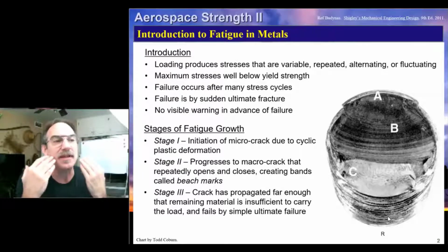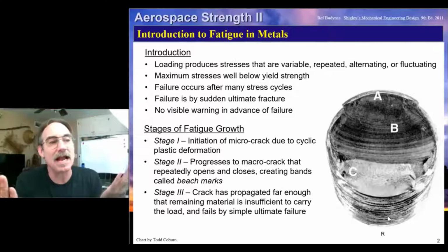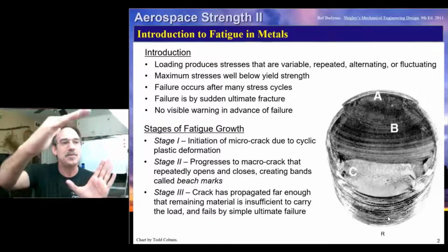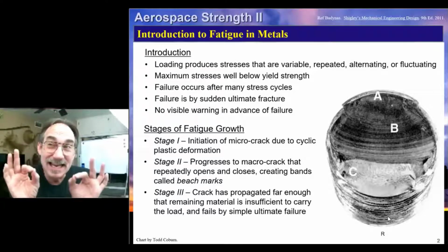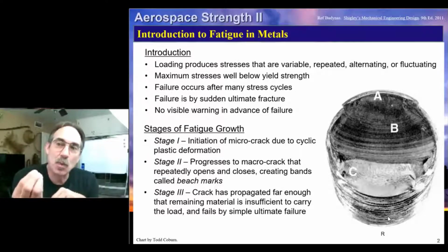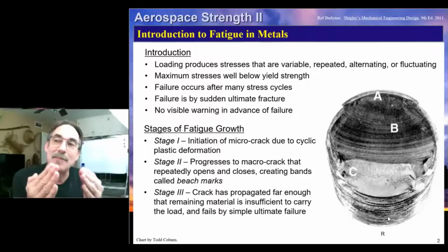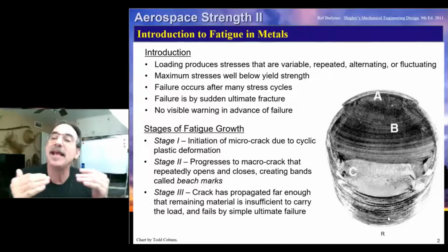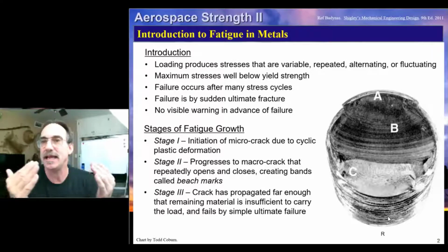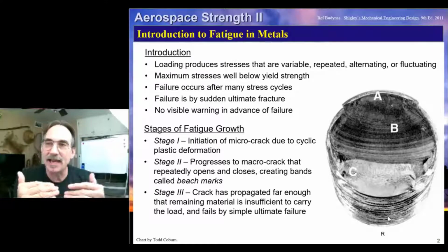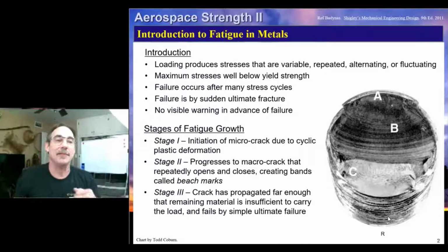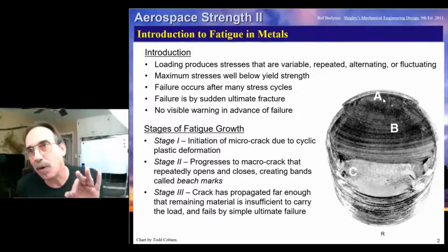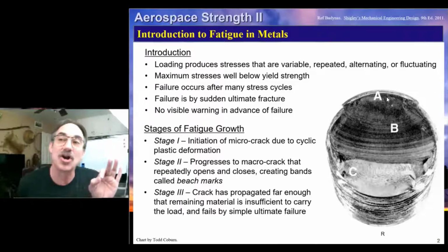If we look at this sample, we say, where did this damage start? With less experience, it's hard to tell. But notice these beach marks. What happens is, with fatigue, we have a place where the problem starts, and then it propagates. And it propagates slowly, so it leaves indication of what's happening. If you look at A here, that's actually where the problem started.